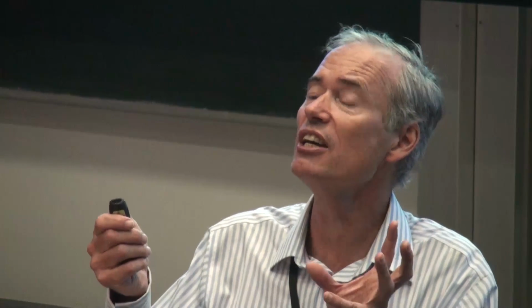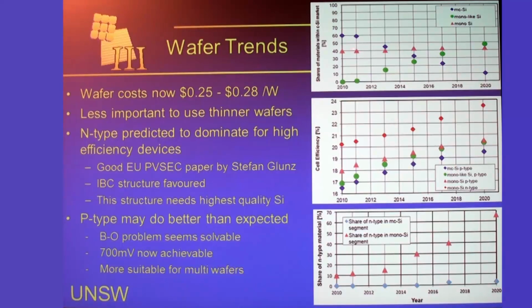And that is where you seed the growth of the ingot during the casting process. We call it seeded cast wafers or cast mono wafers. By seeding the casting process, it means that you can actually grow an ingot that is predominantly single crystal silicon, but you can do so without the oxygen that the Czochralski wafers have. So the material that you get from this casting process, shown in these green circles here, that's expected to dominate into the future because it's still lower cost than Czochralski wafers, but it achieves probably at least as good a quality silicon wafer as what the Czochralski is able to do.